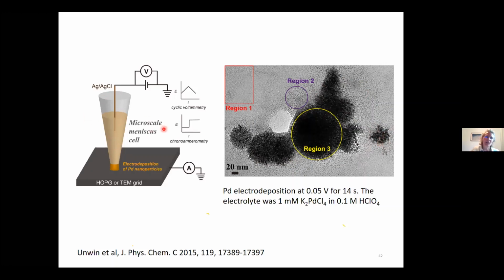But it also flags up where we could go with this, which is basically taking the BDD-TEM grids. You can see the amazing resolution you can get, the real nice contrast against the boron doped diamond background, the ability to very nicely resolve the single atoms to single atom count. And you can imagine with this combinatorial approach, really creating a whole suite of nanostructures across that surface with variations in potential, time, electrolyte conditions, that you can really start to go and look and start to profile what's going on in some of these electronucleation and growth mechanisms. So this is an area we're really interested to try and develop. So if anybody out there is really interested to work with us on this, please just drop us a line and we'll see what we can do.